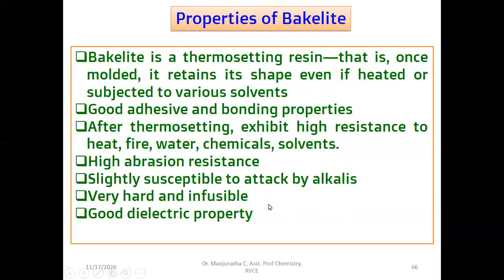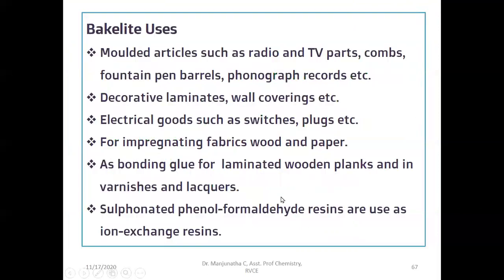It is very hard and infusible, and it has very good dielectric properties. Therefore, it is used in most electrical devices. It is used in molded articles such as radio and TV parts, pen barrels, and phonograph records. It is used as decorative laminates, wall coverings, and electrical fittings such as switches and plugs. It is also used as a bonding glue for laminated wooden planks, varnishes and lacquers, and sulphonated phenol-formaldehyde resins are used as ion exchange resins.